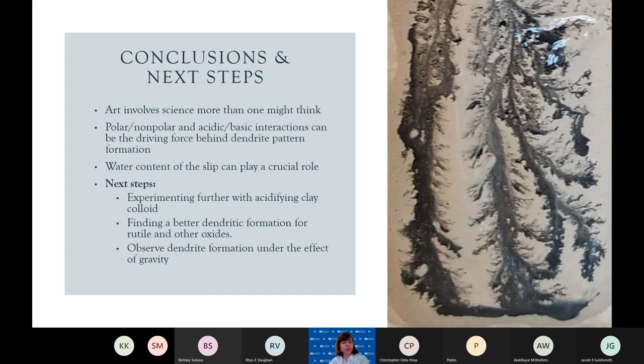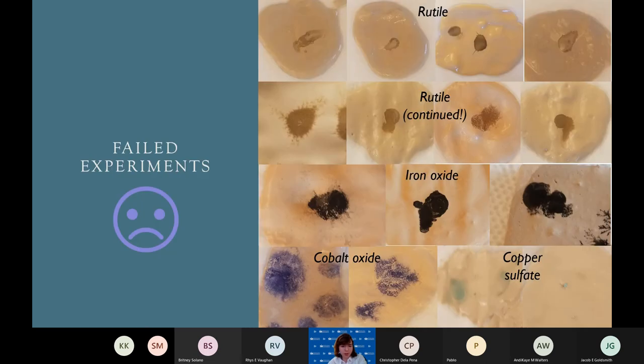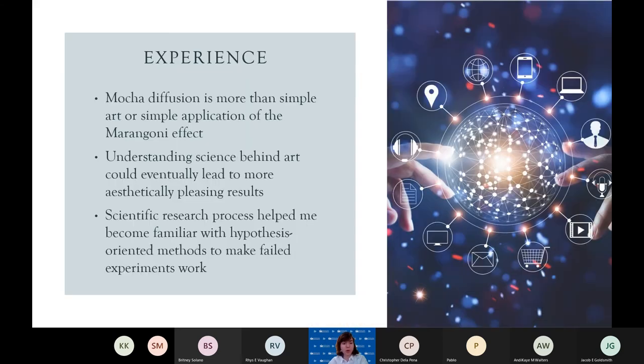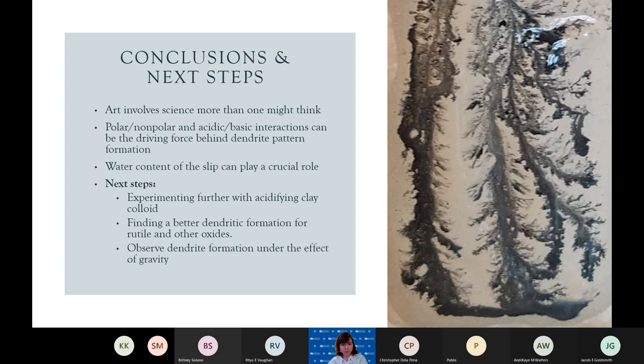Speaking of which, the figure on the right is the result of a gravity effect. If you go back to the slide with the third picture of iron oxide — on a horizontal surface, when it was dripped, it created a blob and wasn't really dendritic. However, when we turned the test tile over to a vertical position, it formed beautiful dendrites going down. So gravity is definitely something that should be experimented with going forward. Plus, considering that clay vases or bowls are not horizontal — they're typically vertical — a gravity effect would have to be observed to produce results on real pottery.